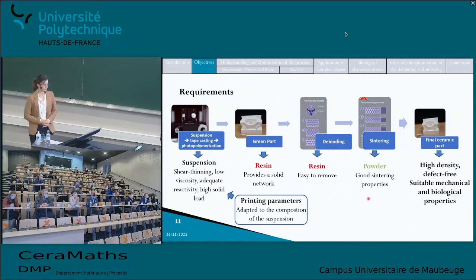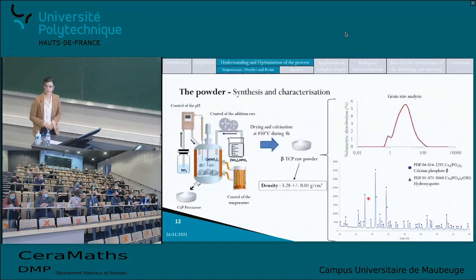So the first step in the understanding and the optimization of the process was to start with the synthesis of the powder and its characterization. The powder was synthesized here in the LMCPA with the help of Nicolas Sommers, through aqueous precipitation in a reactor, and then went through drying and calcination at 850 degrees Celsius during 8 hours, giving the beta-TCP raw powder with a density of 1.28 grams per cubic centimeter.